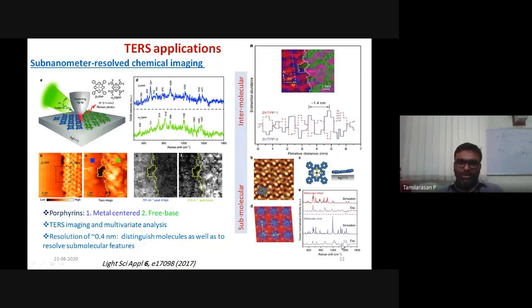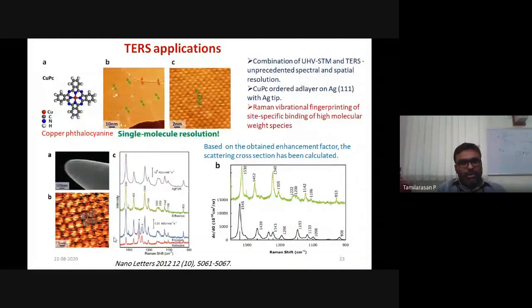Means TERS can go not only up to the intermolecular resolution, it can also go for an intramolecular resolution with the resolution of 0.4 nanometer. It can even distinguish molecular subunits, or you can use it for specific site binding related studies. And a similar study with copper phthalocyanine also has been done for a single molecule resolution. They have formed a thin film of copper phthalocyanine, and you can see here the TERS mapping. And if you just map with the molecular structure, it's saying that each spot, whatever you are seeing here, is a single molecule. Okay?